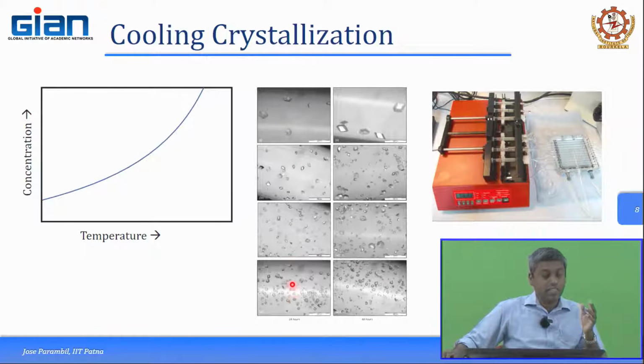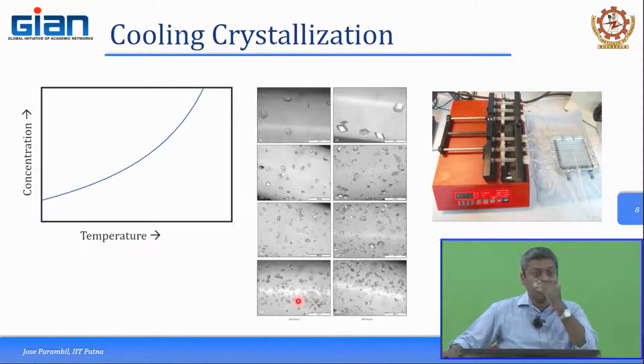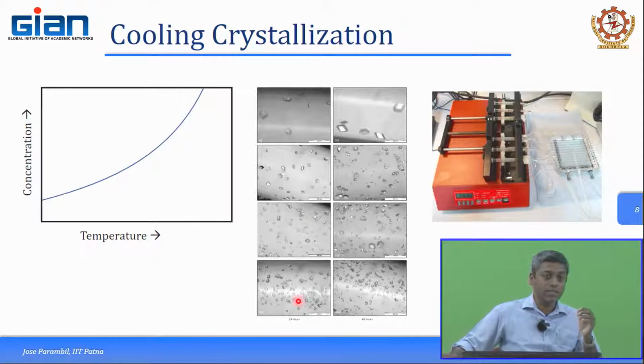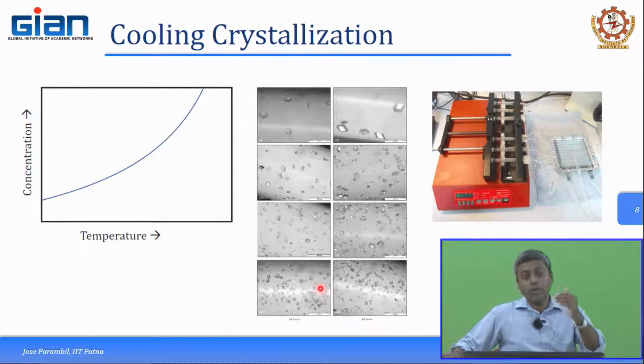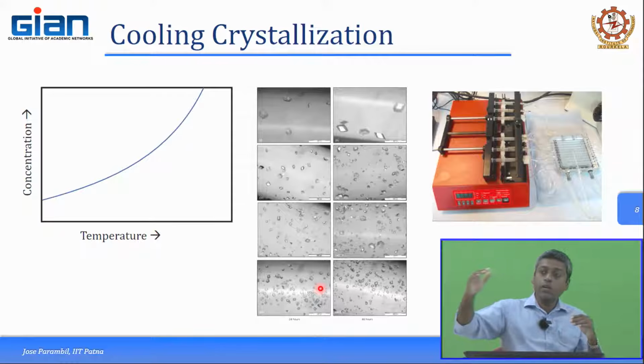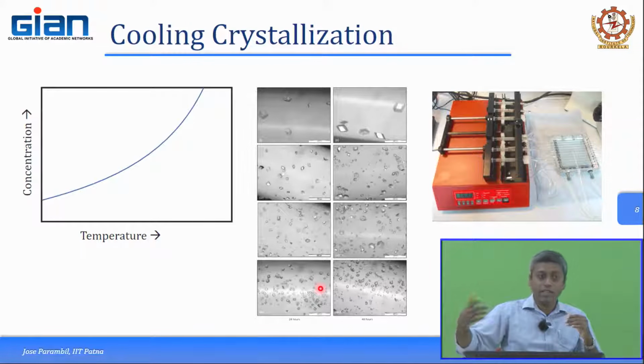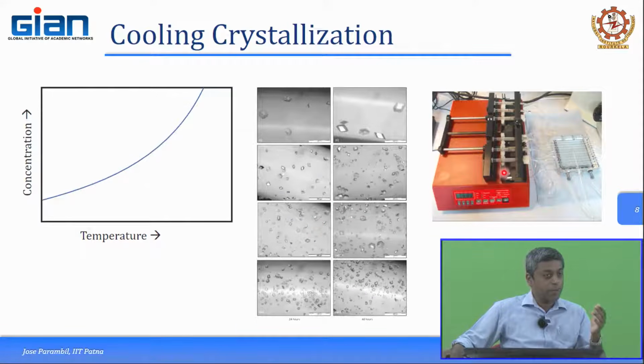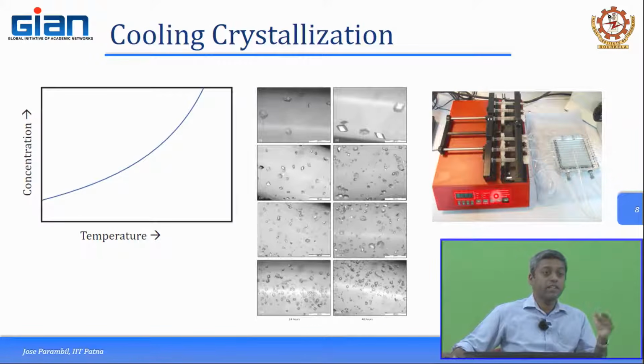So, here you are increasing the flow rate, you can see from top to bottom, what you are doing is you are increasing the flow rate, which changes the residence time as well as the shear conditions or the velocity gradients inside the tubing. And in this particular case, for example, as you increase the shear, you are getting more and more crystals, which means that the nucleation, or the birth of new crystals, is being affected by the shear. There is an optimal shear up to which the crystallization or the nucleation increases. Beyond that particular shear, it starts to decrease further, and if you increase the shear further, it might even degrade the system. So, for example, we have tried, instead of giving a syringe pump like this, putting a peristaltic pump for a continuous operation.